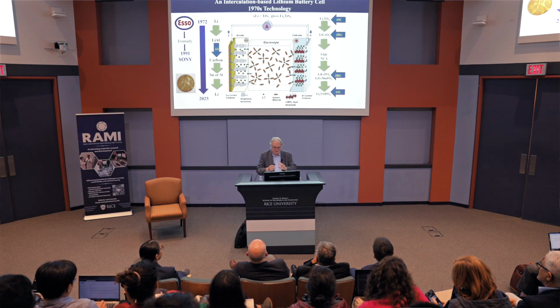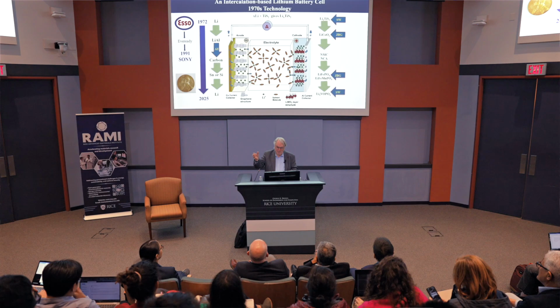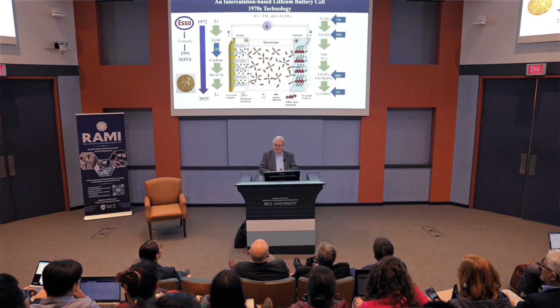So John spent his summers in New Hampshire, away from the Texas humidity and heat. And he came back and said, where's this compound? Well, we couldn't make it. We got this impurity. Well, he said, make the impurity then. And that was lithium iron phosphate. So they invented lithium iron phosphate,